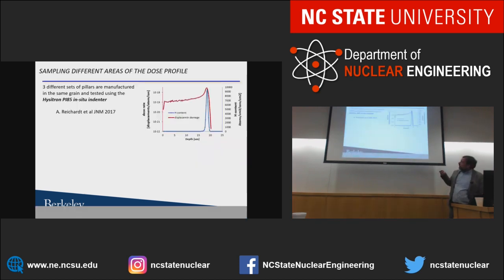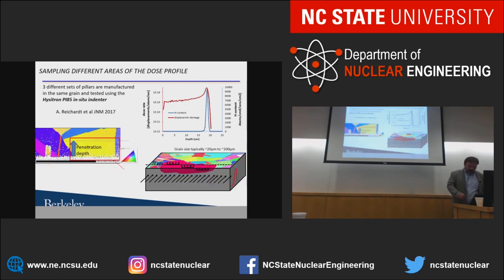We did an irradiation of 2 MeV protons into a material. 2 MeV protons reach about 20 micrometers deep into the material. And we did 1 dpa and 10 dpa, and mapped out the grain structure. So 20 microns in the material is this deep. And we perform mechanical testing within the ion beam implanted region and outside of the ion beam implanted region.